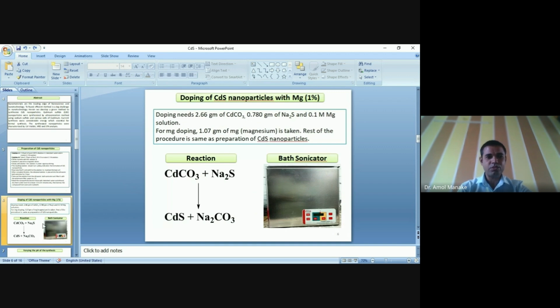We also go for doping. We not only prepared pure cadmium sulfide nanoparticles, we also go for the doping. We dope the cadmium sulfide nanoparticles with 1% Mg metal. And that is the processor, and this is the bath sonicator we use for the synthesis.